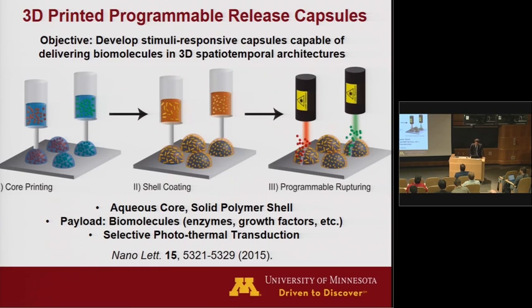And this project actually had nothing to do with 3D printing when we started, but then eventually we realized that 3D printing gives you these advantages because the droplet that comes out of the 3D printer is well defined in terms of volume. So you have total control over the dose in your diffusion equation. You can then 3D print a shell on these things to encapsulate them, and you have control over space because of the three-dimensional control of the 3D printer.